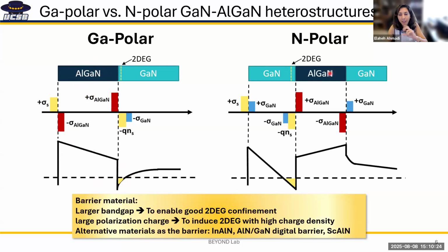Now, if we flip the substrate and use the nitrogen polar side of it, the polarization charges are opposite. So if you just cap it with AlGaN, you won't get any two-dimensional electron gas here. So in a nitrogen polar HEMT structure, we grow the gallium nitride channel on top of the larger bandgap material. So basically this is the back barrier, and the two-dimensional electron gas forms here in front of the AlGaN.